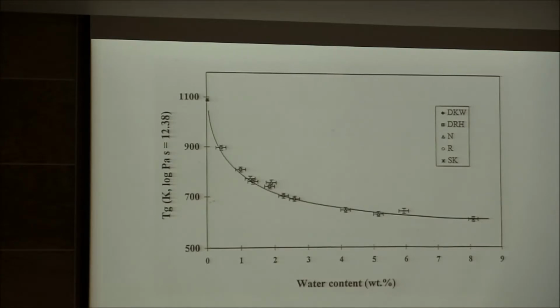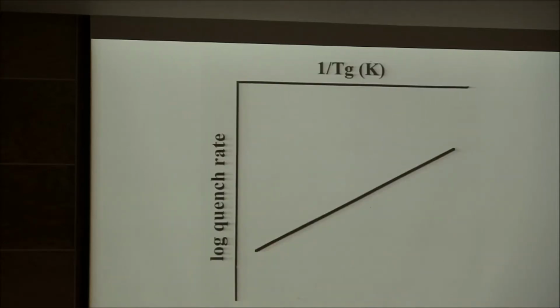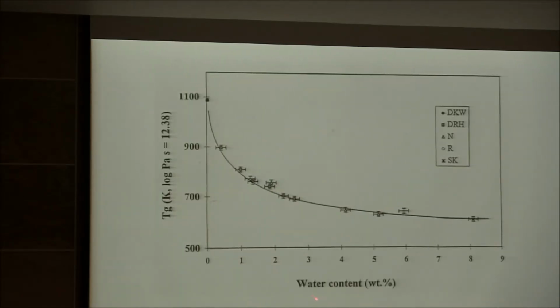This is the most dramatic example of the effect of chemistry on the glass transition that I can give you. There it is. You add water to a silicate melt, and you see that the glass transition drops 400 degrees as a function of a few weight percent of water. So water, and water coming out of that liquid, is the crisis that I referred to before. Now you see quantitatively why it's a crisis, because this solidification temperature of the glass is coming up 400 degrees. Just as you're cooling down, it's coming up to meet you. It's really a crisis.